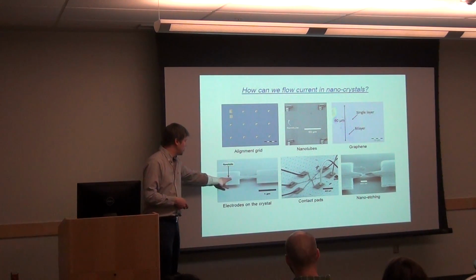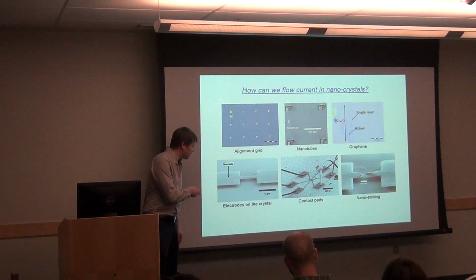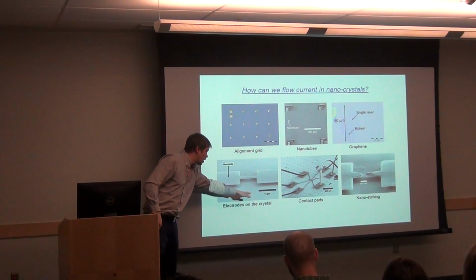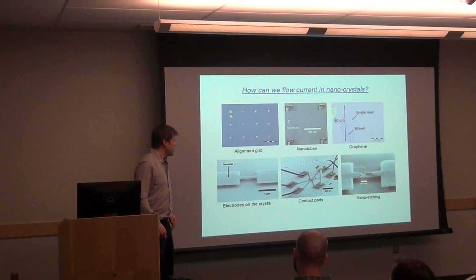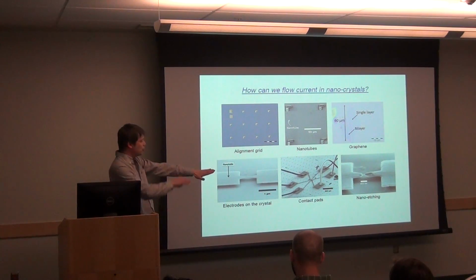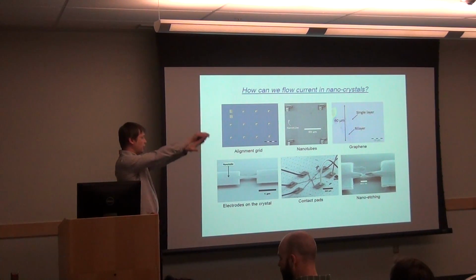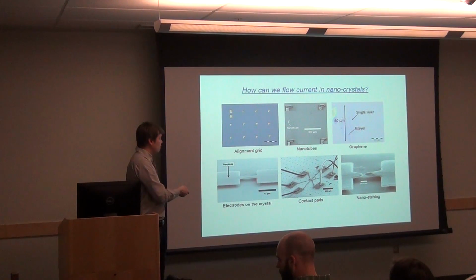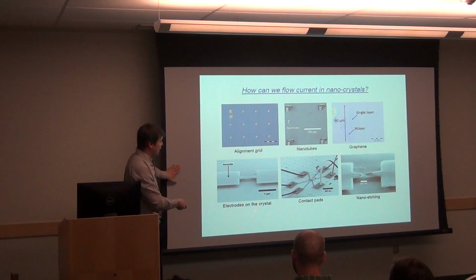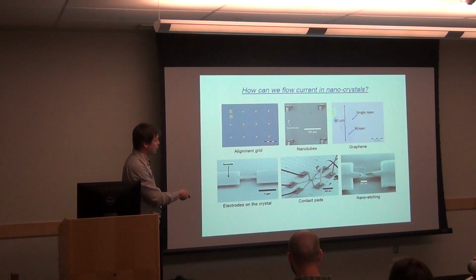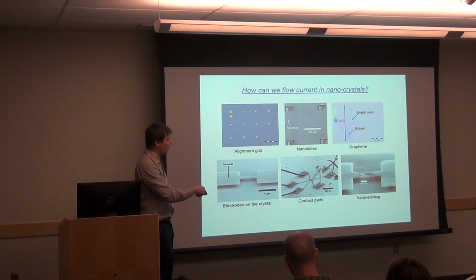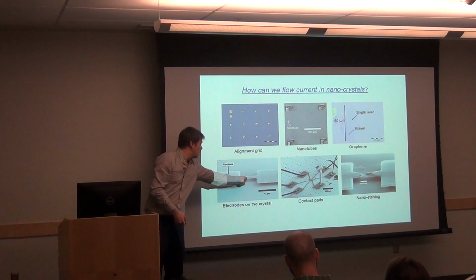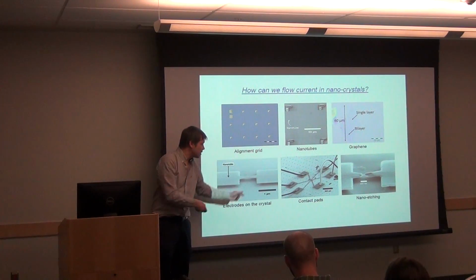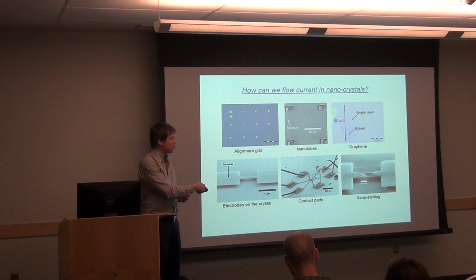So in this case, we put a piece of gold right on top of the nanotube, and then we etch the oxide underneath to suspend the gold. So what you want to think of is a nanotube with a film of gold on top, and both of them are suspended. Then later on here, you have big contact pads that look like this, and you make little solder to them, and then you can flow current through these devices. And if you flow the current the right way, you can actually just electromigrate, move away the gold atoms, and reveal the little carbon nanotube channel. So now you have the source, channel, and the drain.